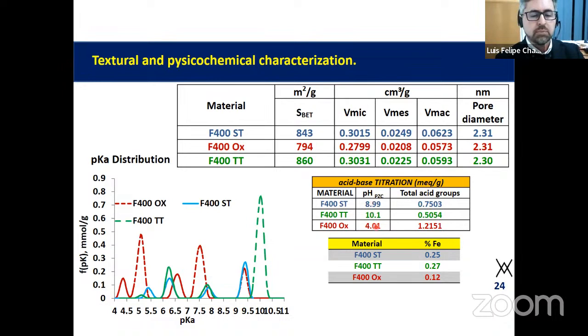Here you can see how the chemical properties of the material change with these treatments. Here are reported the point of zero charge and the total of acid groups, but this material also contains a small percentage of iron oxides, which contribute to the chemisorption of arsenate. So the texture will not influence considerably the performance of the material, but instead the surface chemistry.